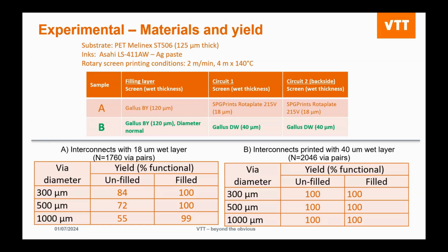But if you want, you can have an additional via filling step with a thicker screen. In this case, the filling layer was 120 microns to ensure that you're getting nice filling of the via. But if you notice, even without the via filling step and the thicker metallic trace printing, you were still able to fill the vias with really high yield. Looking at over 2,000 via pairs, we're at 100% yield. So that means that, unless you need a very thin printed trace, you don't necessarily need to do an additional via filling step.